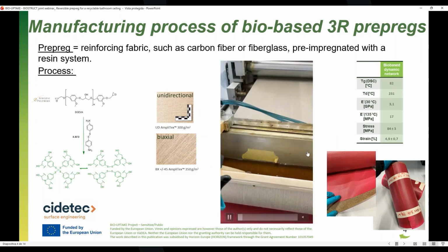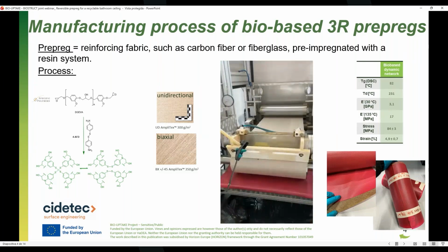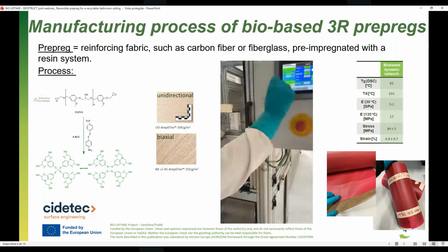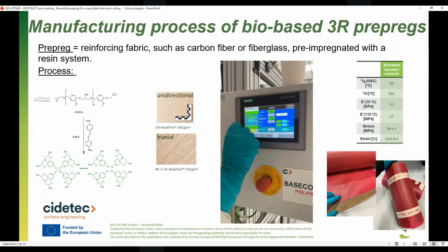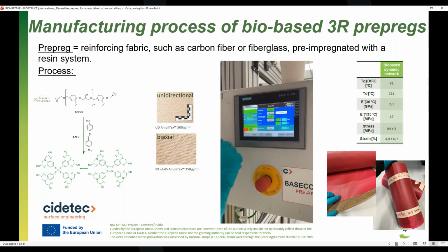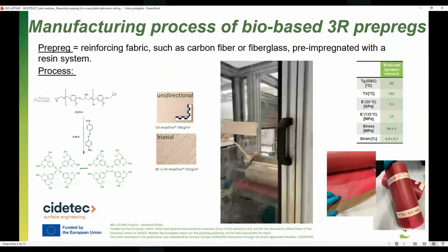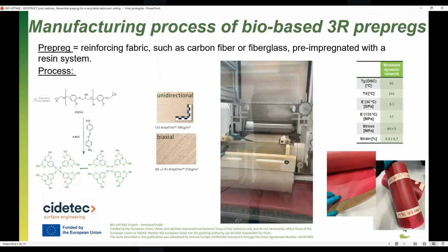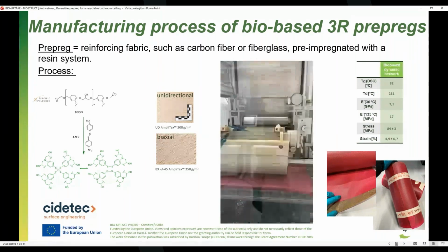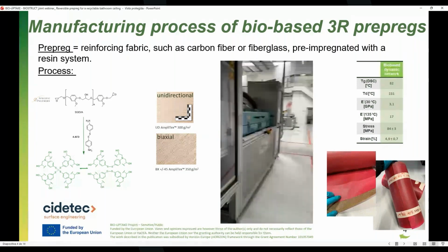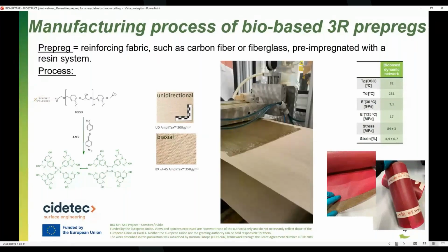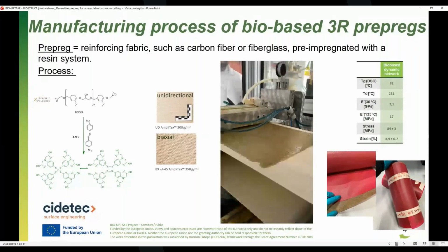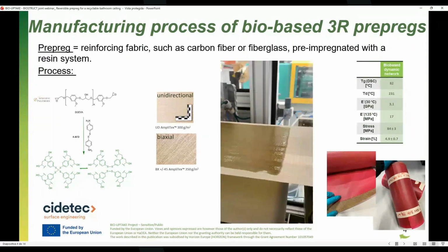So in the BIO-UPTAKE project, what we have done has been to manufacture this kind of prepregs, but using bio-based materials. For the resin, we used a bio-based epoxy resin that was supplied by Specific Polymers. And we have used it to formulate a 3R epoxy system, which is recyclable, reprocessable, and repairable. Using this epoxy system, we have impregnated flax fiber, and we have obtained the prepreg rolls that we were looking for.